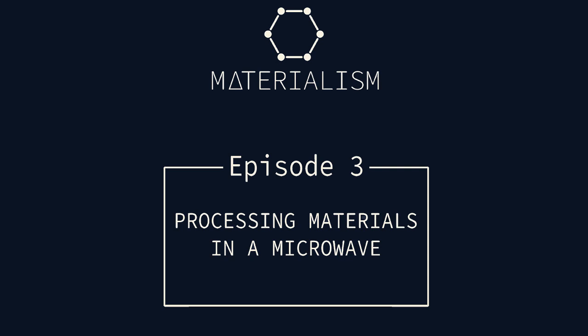Think of how long it takes for something to cook or thaw in a conventional oven. Now consider how quickly you can do the same thing in a microwave oven. This shortened timeline can have major implications when it comes to manufacturing. A series of comparative studies were carried out, and it was found that the processing times could be reduced by as much as 200 times, which of course led to massive energy savings of nearly an order of magnitude.